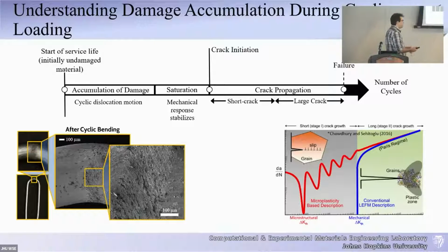And you can really quantify and predict when failure is going to happen if you have a large enough crack that you can measure and quantify. Everything that happens below that, we have very little understanding of how they all correlate together. How does the accumulation of damage lead to saturation? What happens during the saturation that eventually leads to crack initiation? How do the cracks eventually propagate when they're short, that eventually some of them become those large cracks and propagate?